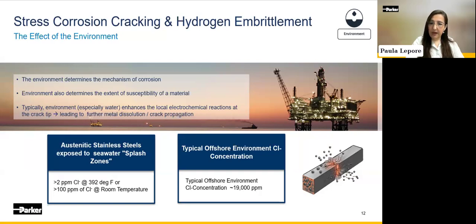For example, when you think about a typical offshore environment, it has chloride concentrations at 19,000 ppm. And it's been proven by lab testing that conditions with concentrations as low as 2 ppm of chloride at 390 Fahrenheit or higher, or as low as 100 ppm at room temperature, will cause stress corrosion cracking and hydrogen embrittlement. This proves how susceptible most systems are to these mechanisms of corrosion when submitted to a typical offshore environment.